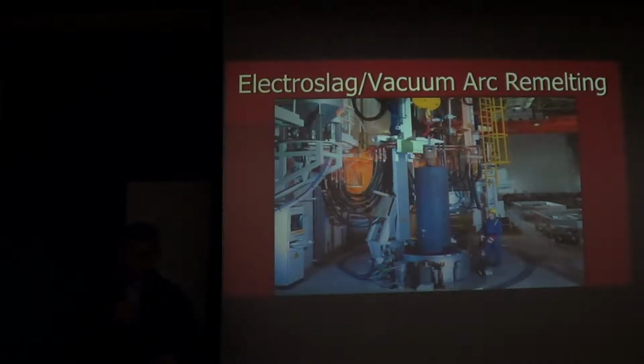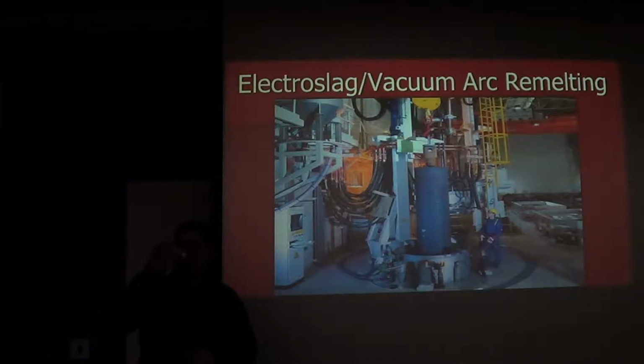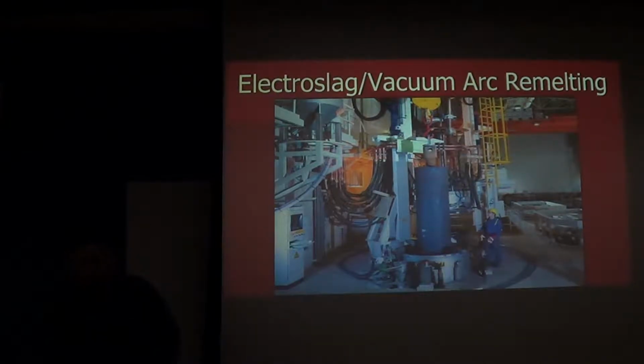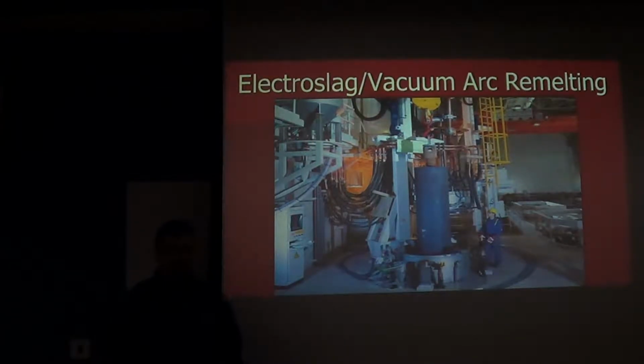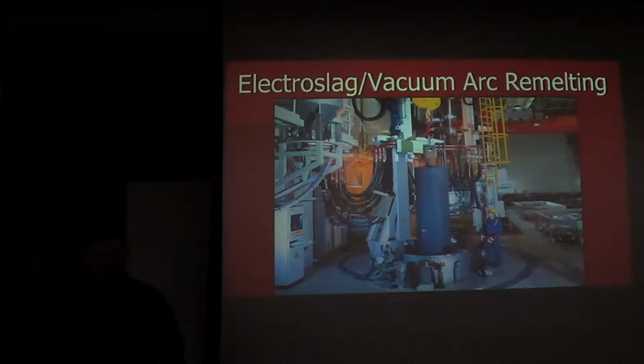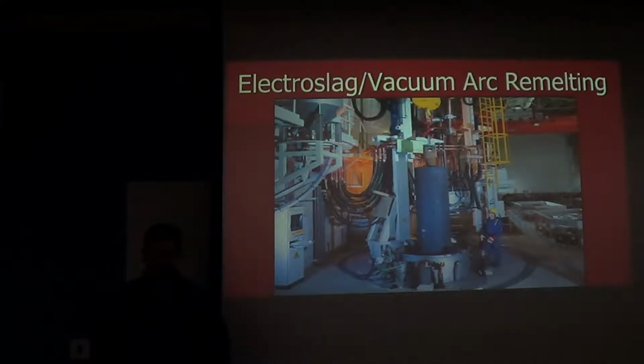It's very, very cool. The problem is titanium melts at 3,500 degrees, so we're above our refractory temperatures. So you have to melt it in this, and you can't ever have a whole bunch of liquid because it's up against water-cooled copper. So in order to get a uniform cross-section, then they forge these ingots out. Oh, yeah. So I saw the ingots that you guys receive. I've seen some ingots.